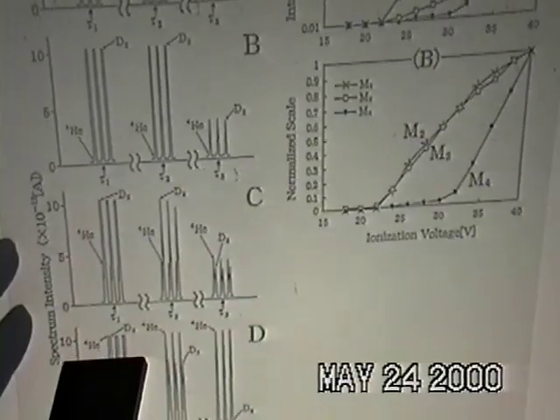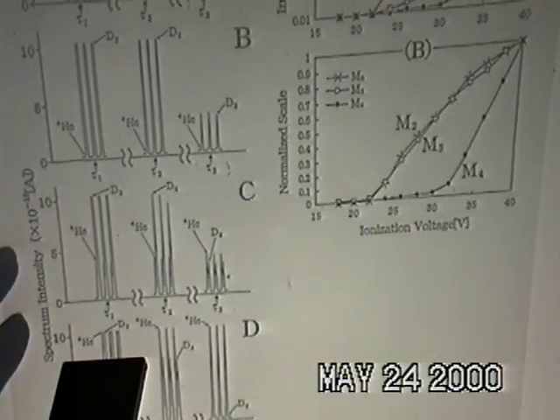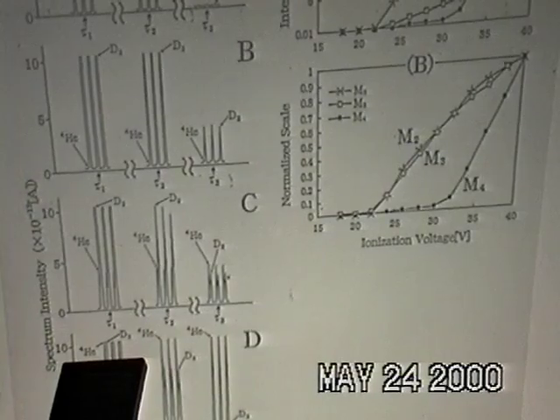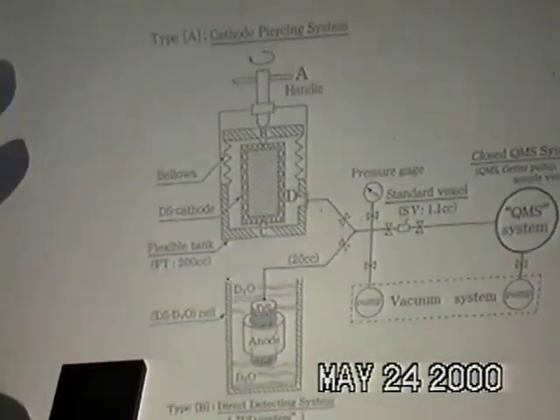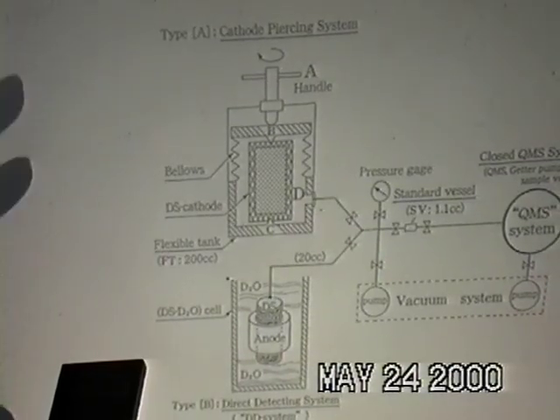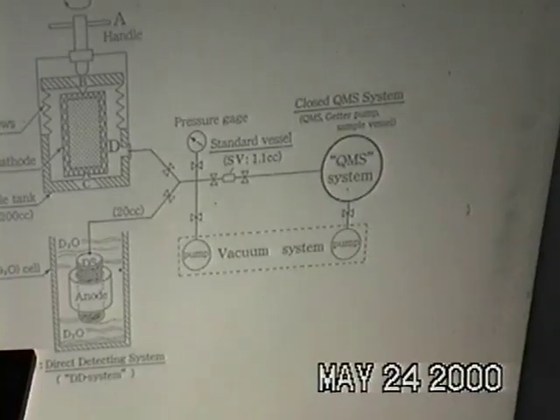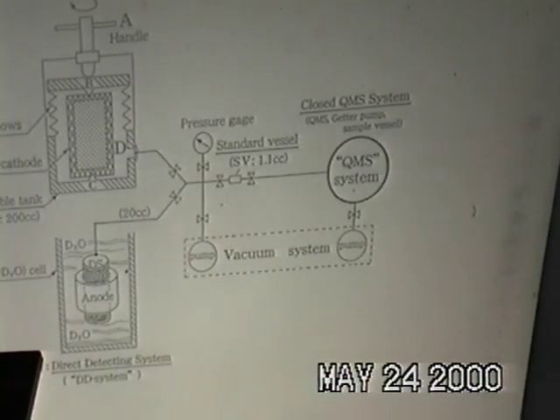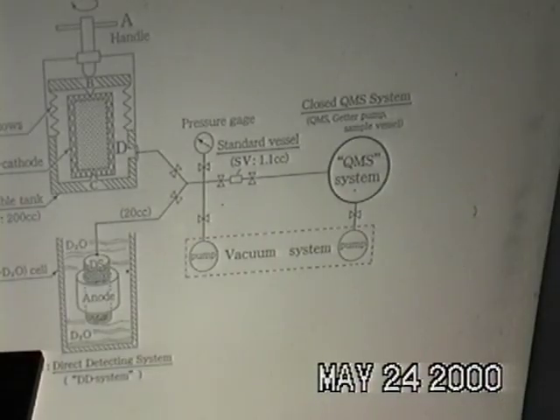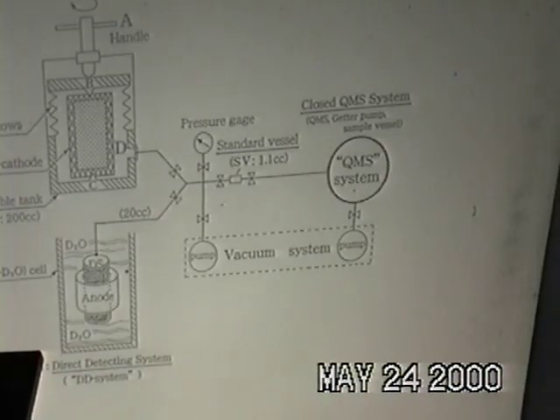In the former method, the DS cathode is set up inside a flexible tank, which is evacuated to high vacuum of 10 to minus 9 to 12, and then the DS cathode is pierced to make a small hole about 20 microns in diameter from outside. In that method, the inner gases of this cathode are measured directly during electrolysis. In this case, the inner gas pressure was monitored by a pressure gauge.